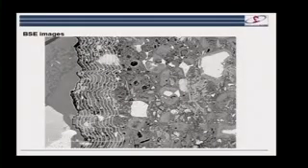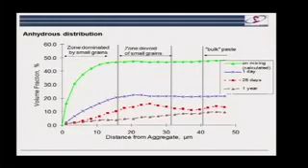And we can measure these effects. We can take an image and we can make these little bands, and we can measure the amount of all the different materials in these different bands. And we can look, for example, at the distribution of the cement grains, and this is just the quantification of what I showed you in these images, that as we approach the aggregate surface, we get less and less volume of cement grains. So the measurements are the blue, the red, and the grey, and the green is what we can back calculate from the different volume relationships.